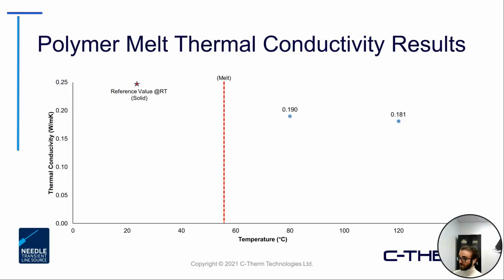But here in this basic data set, we show that essentially in the solid form, the material had a reference thermal conductivity noted there on the left. As it goes through that melt into more of the flowable state, we can see that expected decreasing trend with increasing temperature, at about 80 and 120 degrees Celsius. So this is just one very basic example of how the TLS can be used.